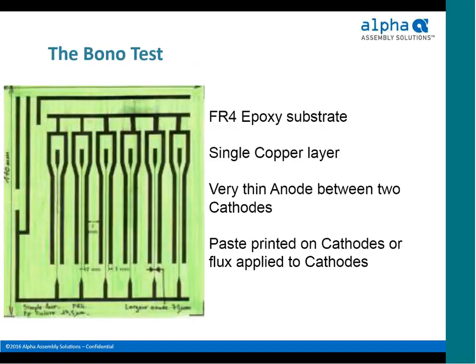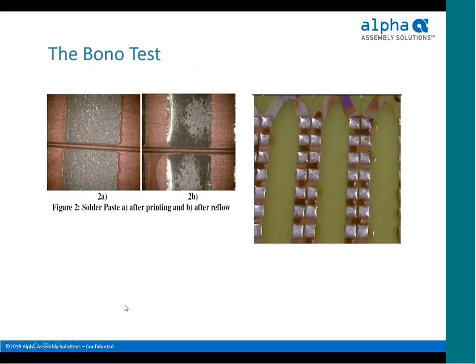What you see here is the anode cathode pattern for the Bono test. I don't know how well it comes across on the screen, but there's a very, very narrow filament that runs through on the anode side, and there are two cathodes that surround it. We'll paste print on the cathodes, or we'll apply flux to the cathodes, and then we'll apply a voltage and condition. See an example of a before and after with the printing on the cathodes.